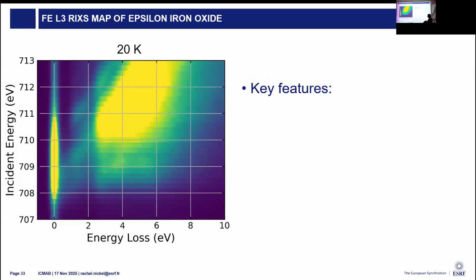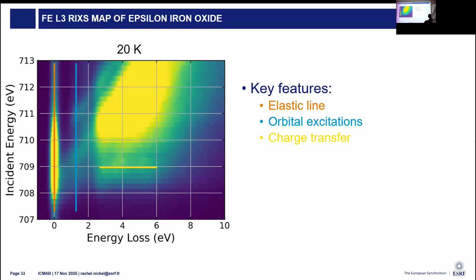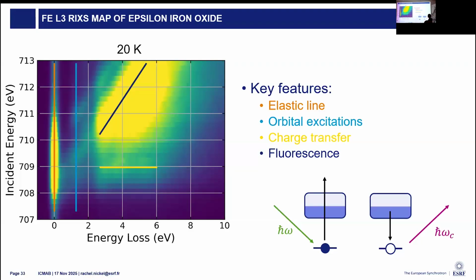As I kind of discussed and broke down the steps before, we have an elastic line at 0 energy loss. There's vertical streaks that show up around the 1 to 2 eV range, which are orbital excitations. And then we have significant charge transfer. So these are horizontal bands that stretch across that reflect iron-oxygen hybridization, as well as fluorescence.